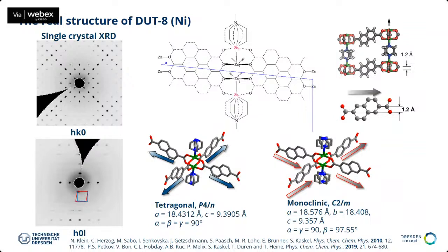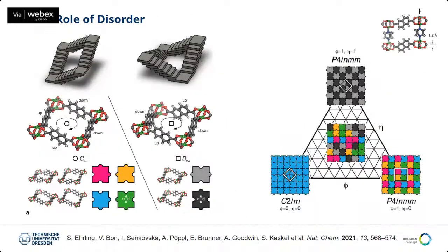So you can have different kinds of nodes where all the linkers step up, or all the linkers are alternating: step down, step up, step up, step down. And in order to rationalize this, Andrew Goodwin in Oxford helped us to rationalize this in this kind of staircase architecture. So you can rationalize the disorder in the structure by identifying structural motifs that are down, down, up, up. Or there are also structural motifs, rings, that are down, up, down, up. So here it's alternating. These are alternating rings. And we symbolize these rings as tiles which are gray.